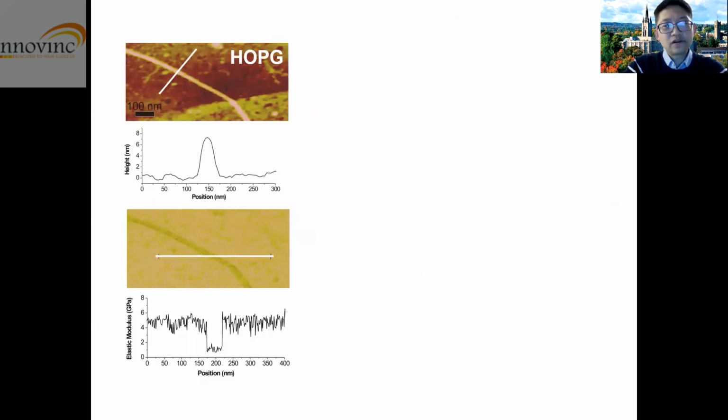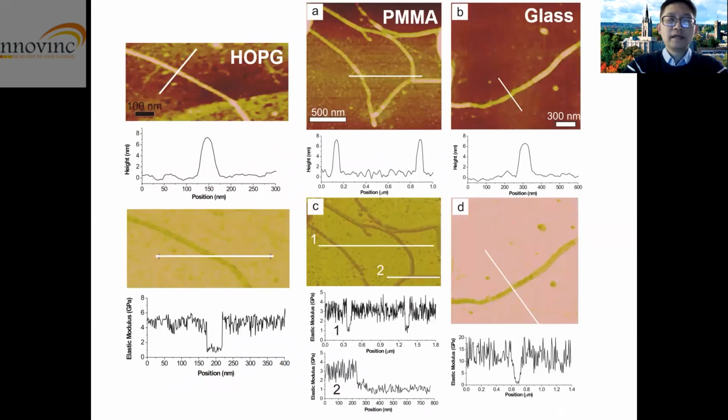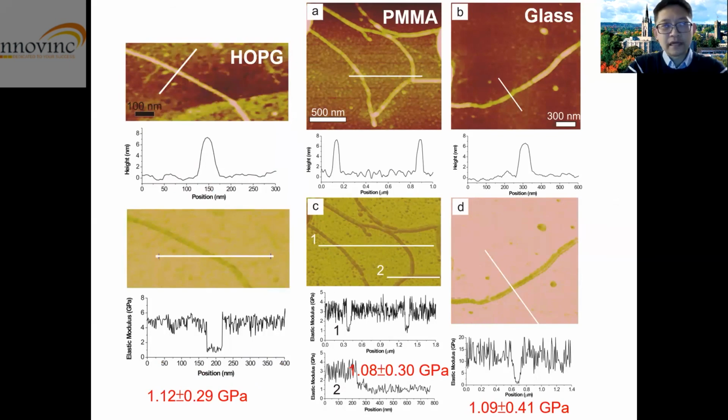Then further, we characterized the elasticity of the bacterial nanowire, and we found the elasticity similar to most polymers. So we think this bacterial nanowire is conductive as silicon, but flexible as elastomer. Which indicates this kind of bacterial nanowire can be used for organic electronics.